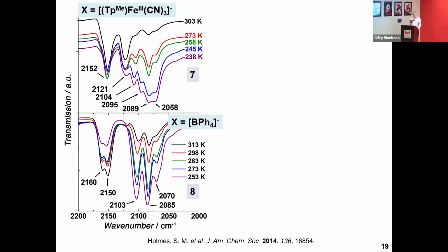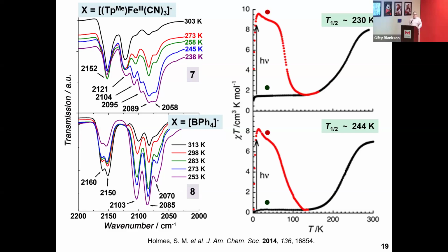But suffice it to say, high energy iron 3 cyanide, cobalt 2 goes to iron 2 cyanide, cobalt 3, just as before, slightly different. Magnetic properties show a transition. The halfway point is here, called T1/2. For this anion substituted derivative, it's 230 Kelvin. This one is 244. And this allowed us for the first time to also describe that the anions, while they do play a role in the electron transfer, that's not the business end of the behavior. What's happening is within the molecule.